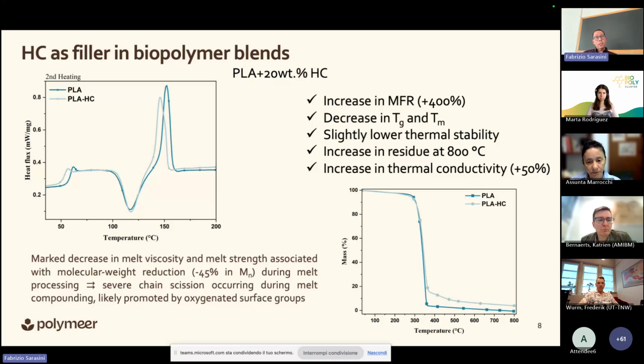At first, we detected a significant increase in melt mass flow rate, and a decrease in the glass transition temperature and melting temperature of the neat PLA, associated with slightly lower thermal stability. This was also accompanied by an increase in the residue, and an increase in the thermal conductivity of the composite. That's why I was mentioning that this can be considered a multifunctional additive. One of the major concerns was the significant decrease in melt viscosity and melt strength, which was ascribed to a significant reduction in the molecular weight of the PLA, likely caused by the presence of these oxygenated functional groups, which acted as scission points during melt compounding.